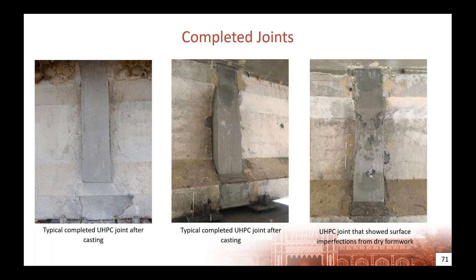And then I'll talk more about this in the lessons learned, but in the picture on the right, the joint looks kind of scarred. The surface of it tended to attach to the formwork, and as the formwork was pulled off, it took this surface layer off. We investigated it, and it was really just superficial damage on the surface, but because UHPC has a very low water to cementitious material ratio, it tends to leach moisture pretty fast, and if it loses moisture, it doesn't cure as well. So this tended to happen when the formwork wasn't prepared properly.